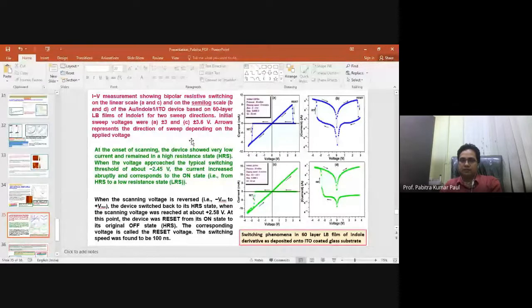IV measurements were performed, and you see at minus 2.45 the current increased abruptly when going from plus bias to minus 2.45, and it is called the on state. So the on state is from the high resistive state to the low resistive state. Memory requires different states, so resistive memory has on or off states, and also retention of the on and off state after withdrawal of the bias potential.